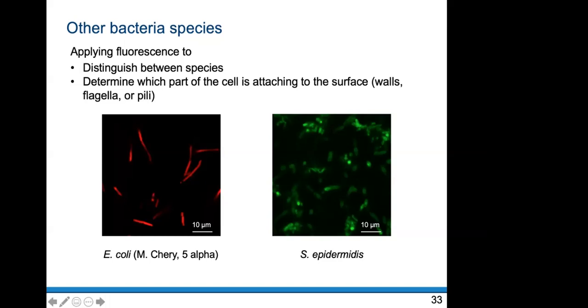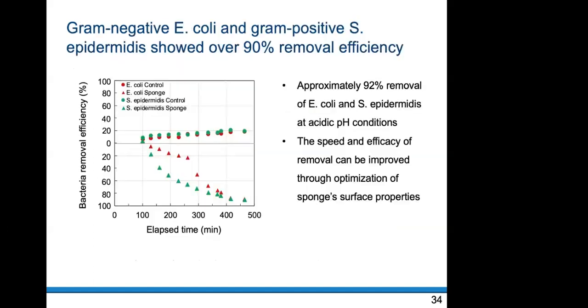And here this is Staphylococcus epidermidis. This is a gram-positive bacteria, and this one attaches to the surface via surface wall, which has alkyl groups. So we also examined these 2 bacteria attaching to the sponge surface. As you can see, once again in the control experiments, the concentration of the bacteria remained almost constant, only varying between 0 and 20%, meaning it started at 0 but over time about 20% of the bacteria grew. But when we use the sponge, these 2 lines, about 92% of the bacteria attached to the sponge surface.